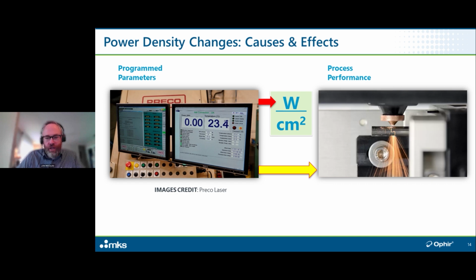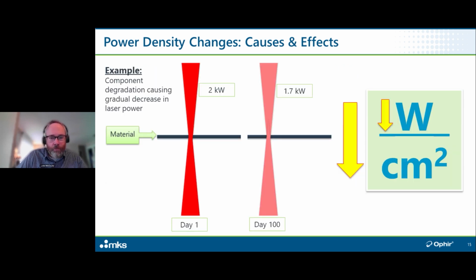You can reduce, your power can be reduced. So you program 4 kilowatts into the laser, but because of some kind of defect in an optic or something else happening with the laser system, it could translate into 3.5 kilowatts into the process, which decreases the power density. You could have some kind of focus shift on the laser system, which increases the beam size, which will change your power density as well.